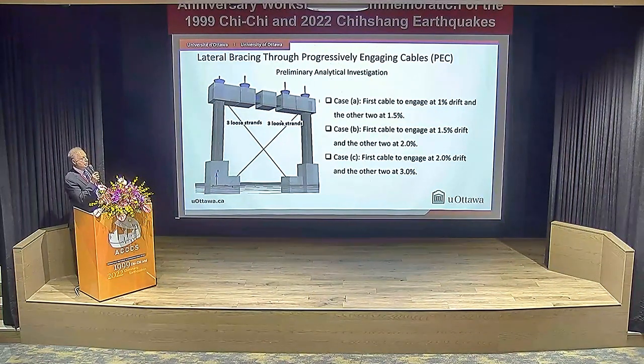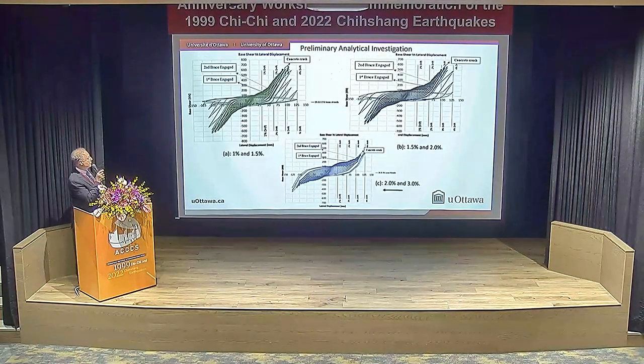We did some tests as proof of concept, and it seems to work beautifully, but before we did that, we did some analytical research, and we looked at 3 cases. In each case, like case number 1, we had 2 cables. First cable would engage at 1% drift, second one at 1.5, and then we looked at 1.5 and 2, and then 2 and 3 different levels. So before a technique like this can be used, obviously one has to establish drift capacity of the non-ductile frame. And here you see at different levels of engagement, the stiffness changes as expected.